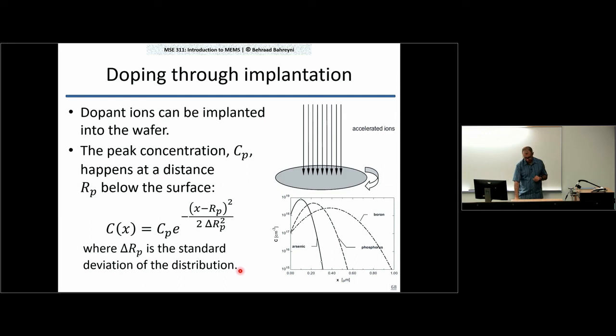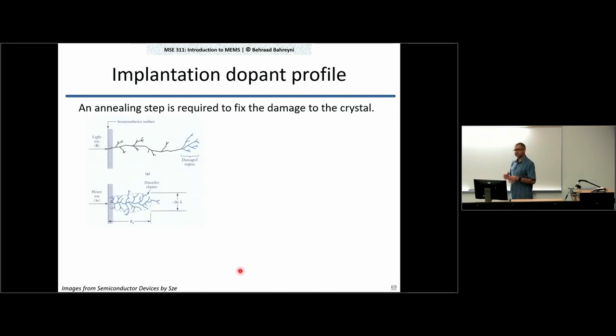It's that easy. Now the challenge here is that you are bombarding a nice clean crystal with these high energy ions. They're going to create micro cracks in your crystal. And because of that, you will have a damaged structure at the end of implantation.